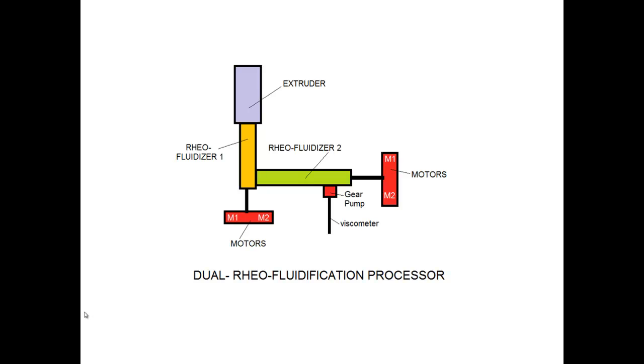Now, all the benefits of a previous design for a rheofluidizer can be seen, as I said, by a lowering of the processing temperature. I can lower the processing temperature of a melt by approximately 100 degrees and still have a melt which is flowable. I am describing this in the papers mentioned at the beginning in the Journal of Macromolecular Science Physics. There's a couple of papers on rheofluidification.